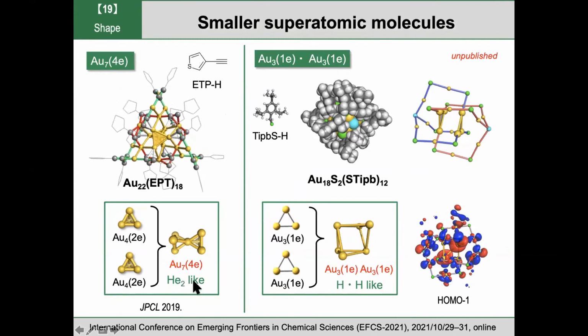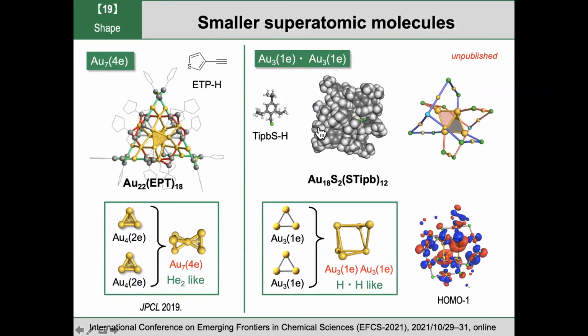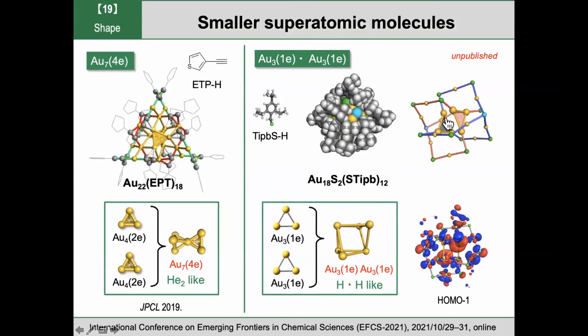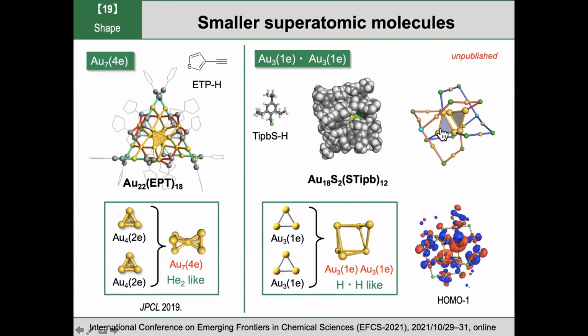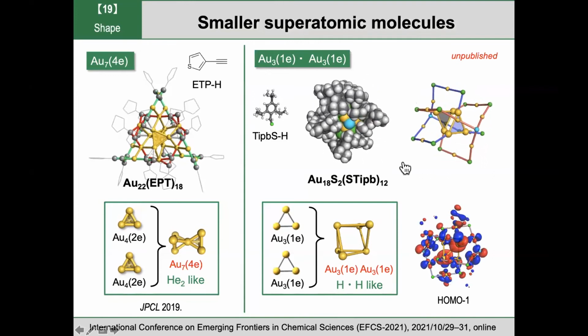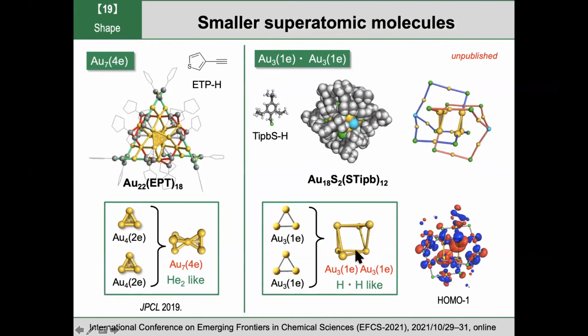And if we use more bulky ligands, we can get this. If you look at the framework, you can see this very unique structure. A gold trimer forms a pair, and the gold-6 core cannot be viewed as octahedral. It is highly deformed, and we can see this pair is not bonded to each other. As you can see here, there is no overlap in the orbitals. So the bonding between the two gold trimers is very weak in this case. We think that this core can be viewed as a hydrogen atom pair without any strong bonding. And this is due to the steric repulsion of the bulky ligands.